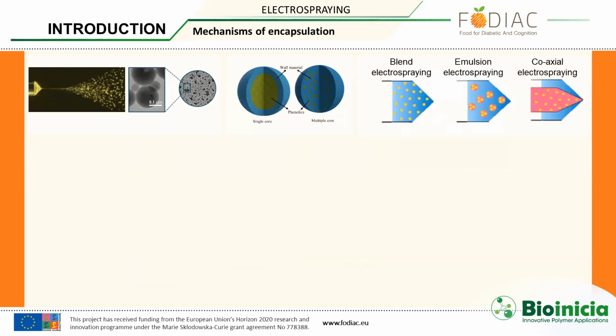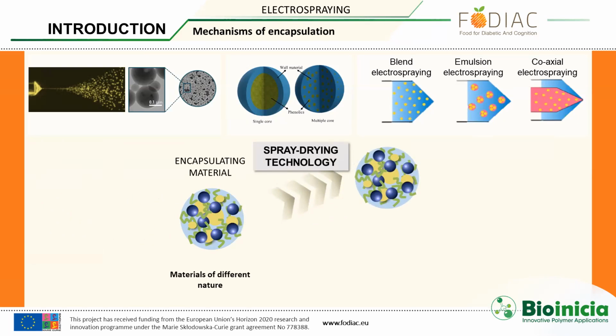When we are talking about electrospraying, this is a highly versatile technology because we can create particles in the nano or the micro scale, and also with different structures, since they can be single core or multi-core, just by changing the needle or the configuration of the nozzle, or changing the solution. We can start from a solution or an emulsion. So it's a highly versatile technology. And we can also encapsulate different kinds of bioactives, being hydrophilic or hydrophobic, in this case polyphenols and flavonoids. And they can also be encapsulated in different types of materials.